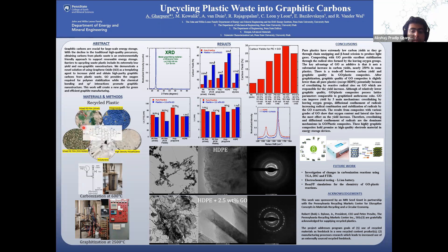As shown in the figure, five plastics were used in the study: shredded PE films, polypropylene pellets, high-density polyethylene flakes, post-consumer recycled PE film pellets, and polystyrene. Plastics were dry mixed with 2.5 weight percent of graphene oxide and loaded in a tubing bomb reactor. Then they were carbonized at 600°C for three hours and the obtained coke was graphitized at 2500°C for one hour.